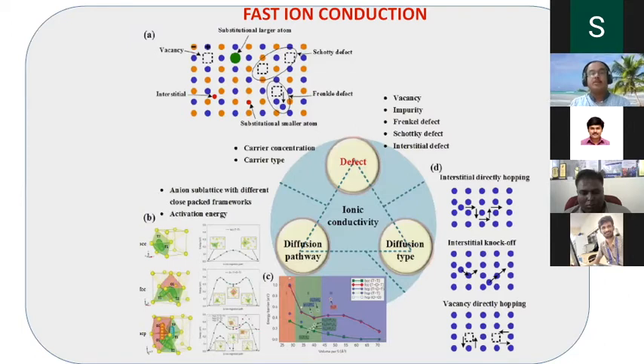So people have to think about the carrier concentration, or what you call the defects. Ionic activity comes starting from here. Defects are diffusion pathway and diffusion time. So many mechanisms: vacancy, impurity, Frenkel defects, Schottky defects, interstitial defects. If you have the defects, then you have to think about the carrier concentration and carrier type. So anions, sublattice, the different close-packed frameworks, this is what you call designs and diffusion pathway. So here, diffusion type. People have developed this theory over quite a long time, and still they work very hard to develop fast ion conduction in materials.